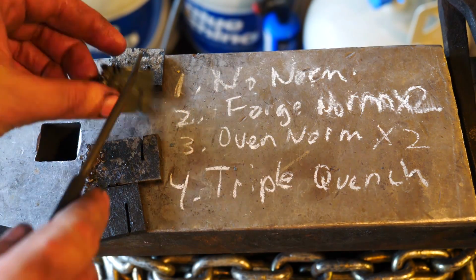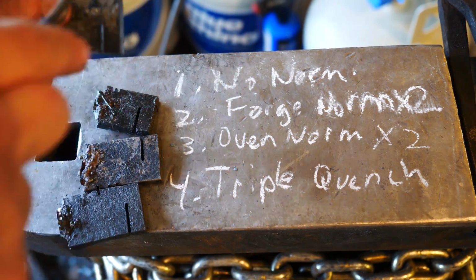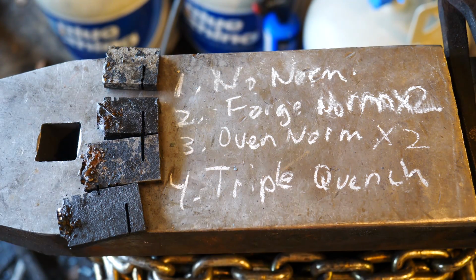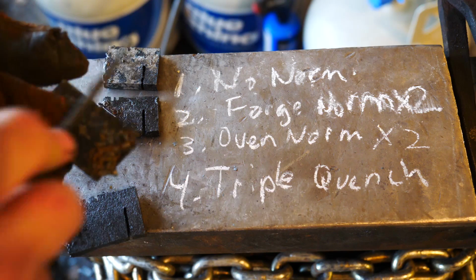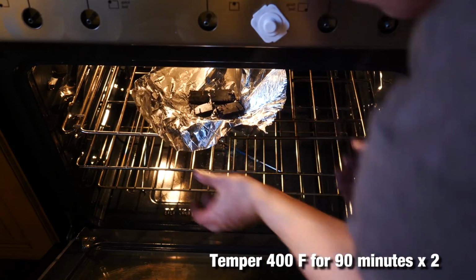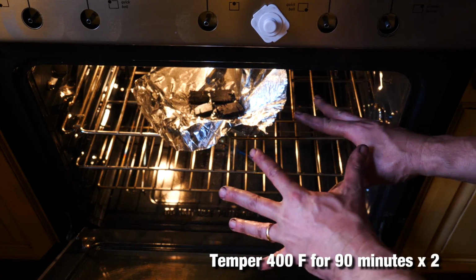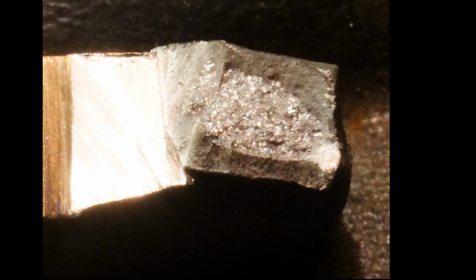Number 3 is still a little hot. But yeah, they all hardened to over 60 HRC. They're going to be tempered at 400 degrees for 90 minutes twice, all in the same oven. Yeah, it's a kitchen oven. Who cares if it's off 10 or 15 degrees? Either way, they're all getting the same tempering cycles, basically.